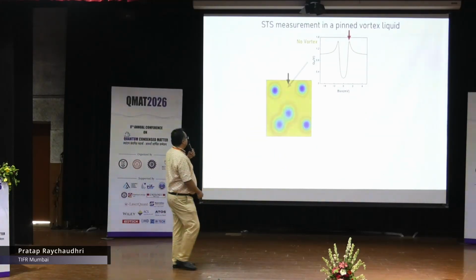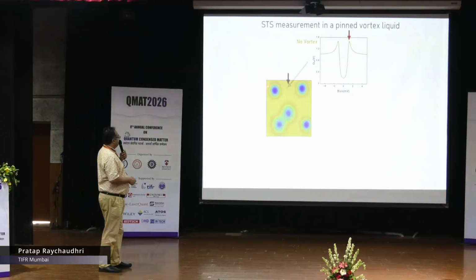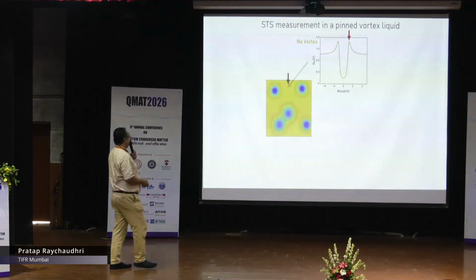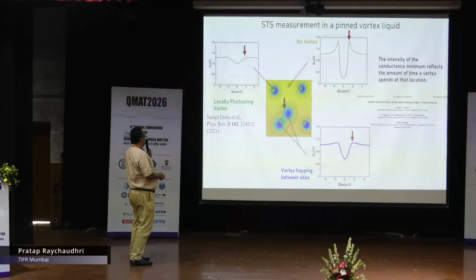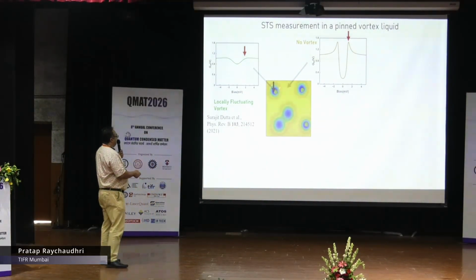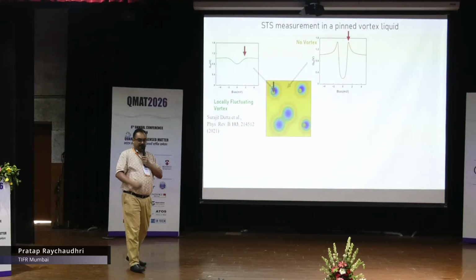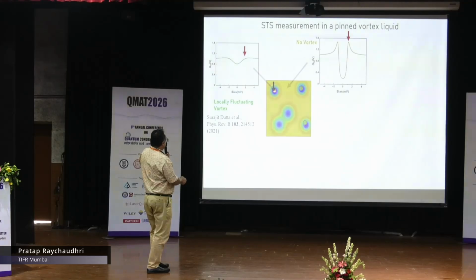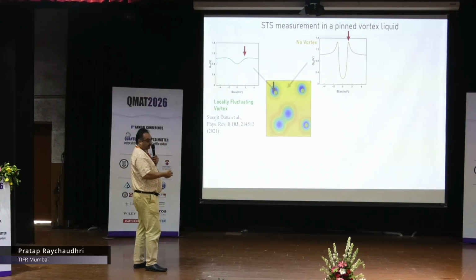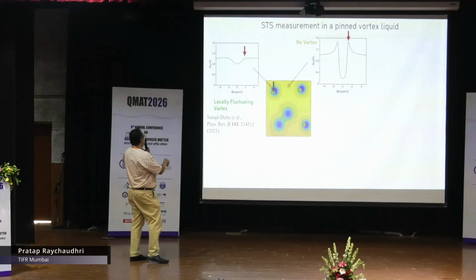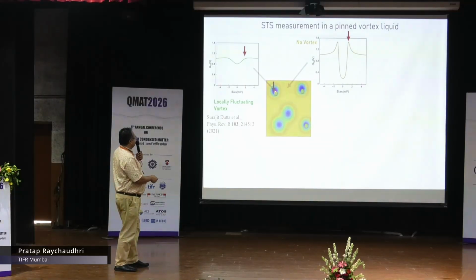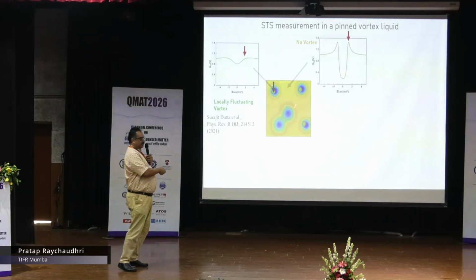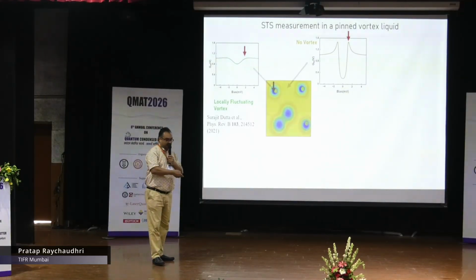Why does this happen? Let me explain this with this cartoon here. If I have a conductance map like this and I bring my tip here where there is no vortex at all, I get a nice superconducting spectrum like this. If I now move my tip here, where I have a vortex which is possibly jiggling around a little bit about its main position, you will find the core under the tip for most of the time, and since this core is a normal metal, your gap will be suppressed and your coherence peak will also be almost suppressed. If the vortex was completely static here, it will be completely flat, but since the vortex moves around a little bit, you might see a small feature.